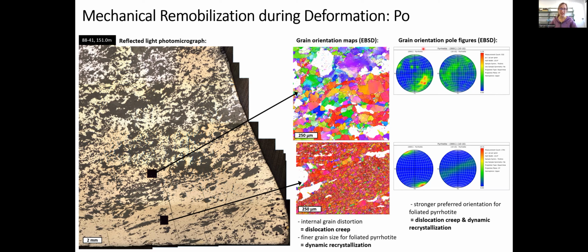And then finally, we can also use EBSD data to plot pole figures showing the orientation of pyrrhotite grains. And you can see in the coarse-grained, less deformed area, you've got a bit of a preferred orientation. That's pretty decent. But in the highly deformed area, it's a much, much stronger preferred orientation. So all of this together suggests that our pyrrhotite was experiencing mechanical remobilization during deformation. It experienced dislocation creep and dynamic recrystallization, causing us to decrease the overall grain size and strengthen the preferred orientation.